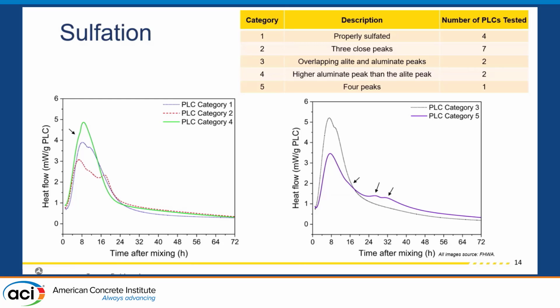And then looking at sulfation, this is coming back to our hydration kinetics. We were able to distribute our 16 different PLCs into 5 different sulfation level categories. Those categories included properly sulfated, 3 close peaks, overlapping aluminate and alite peaks, higher aluminate peak than the alite peak, and 4 peaks. But what you really need to know from this is that with 5 different categories of behavior, that's a lot of differences in the possibilities for performance. So understanding what your behavior might be will also help you understand the performance you should expect.